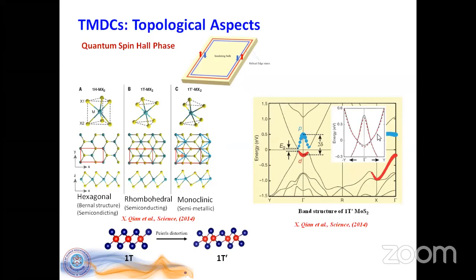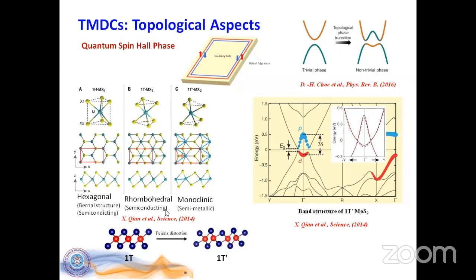Now, once this distortion happens and once one takes care of the spin orbit coupling in the system, there are these exotic changes that happen in the band structure. As you can see, there is this conduction band and the valence band. The black one is basically without taking the spin orbit coupling into account. The moment one includes the spin orbit coupling in the calculation, one sees a camelback-like shape of the band, and this is where quite interesting features come up. You can see here is the band gap, and here is the 2 delta at the gamma point. This is what is referred to in this article, which changes due to this distortion from the trivial phase to this non-trivial phase, which is what the 1T prime is about, showing the quantum spin Hall phase.